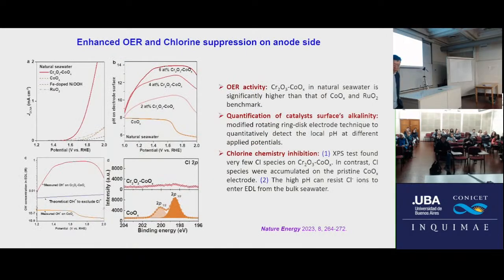Okay, here first we study the OER reaction, the oxygen evolution reaction, on the anode side. For the published results, it is the dashed line. This one is our catalyst. You can see performance is much better. This activity. So why? We use a modified rotating ring disc to measure the pH value on the surface. That surface means only several molecular distances. So you can see, if we use 6% chromium oxide and cobalt oxide, the pH value is 14.